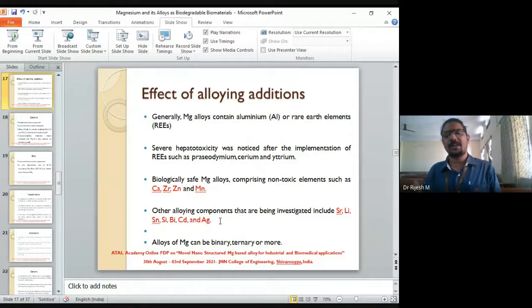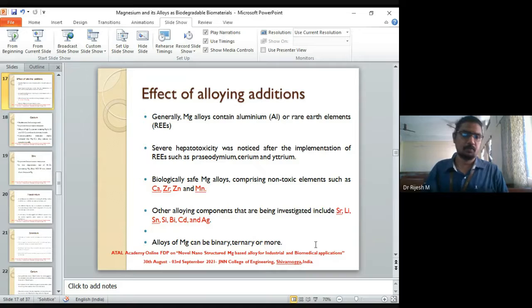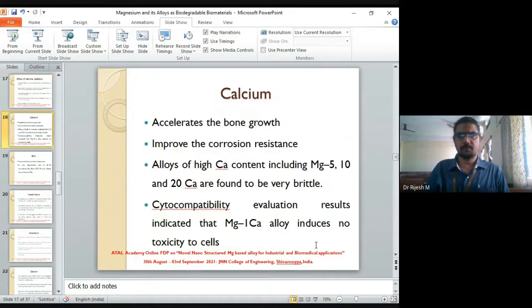These alloys can be binary, ternary, or more. What I mean to say is that you can have more than one alloying addition. When you have only one alloying addition, we call it binary. When you have two, we call it ternary, and it can be more than that too. Calcium helps in accelerating bone growth. Calcium improves the corrosion resistance. That is the prime reason why we are adding these alloying additions: we wanted to improve the corrosion resistance.